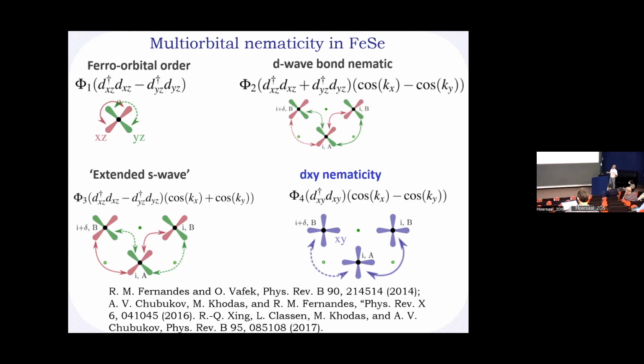Or you also have what you can dub an extended S-wave in the momentum dependence, but the D-wave character is hidden by the phi3 in the combination of the orbitals. Or there is another one which is also allowed by symmetry, which is purely located on the XY orbital and dubbed phi4. And again, this is allowed by symmetry and was initially classified by Fernandes and Chubukov.